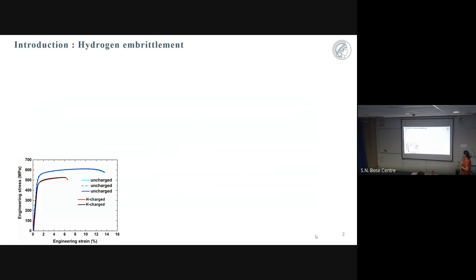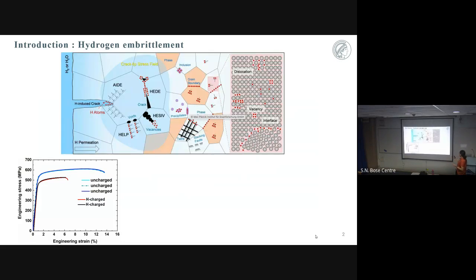So here is a typical stress strain diagram, an engineering stress strain diagram. Here you can see the blue and the red curve are significantly different. Why are they different? The blue curve shows a prototypical aluminium alloy which is not electrochemically charged, and the red one is when it is exposed to hydrogen through electrochemical charging. As you can see, there is a sharp decline in the ductility of the alloy in the presence of charging, and that is our focus. That is why we want to study hydrogen embrittlement, because it decreases the mechanical properties so strongly.